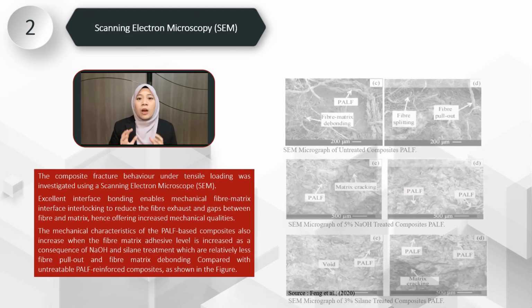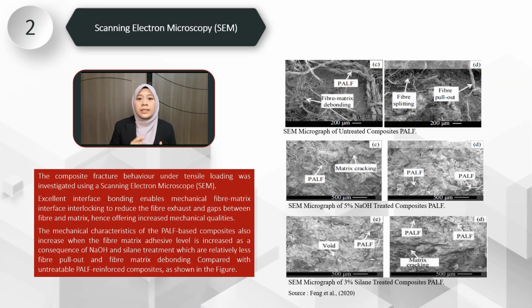Second is SEM. The composite fracture behavior under tensile loading was investigated using a scanning electron microscope. Excellent interface bonding enables mechanical fiber-matrix interlocking to reduce the fiber pullout and gaps between the fiber and matrix, hence offering increased mechanical qualities. The mechanical characteristics of the PALF-based composites also increase when the fiber-matrix adhesion level is increased as a consequence of sodium hydroxide and silane treatment, which show relatively less fiber pullout and fiber-matrix debonding compared with the untreated PALF reinforced composite, as shown in the figure.